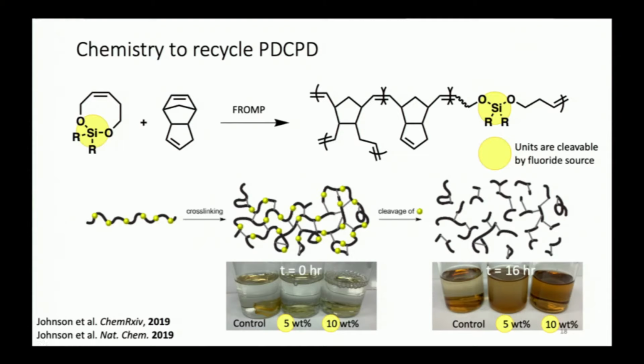This siloxane unit is a very small part of the polymer backbone, and so there is very little compromising of the properties, and it is cleavable by a fluoride source. And so one just needs to be able to mass transfer fluoride to the polymeric material. In a bulk sense, it's going to be a very slow process, but you can see it completely redissolve that polymeric material back to what would be useful materials to build from or be taken apart by other means after